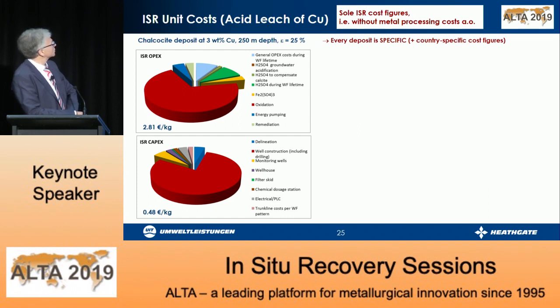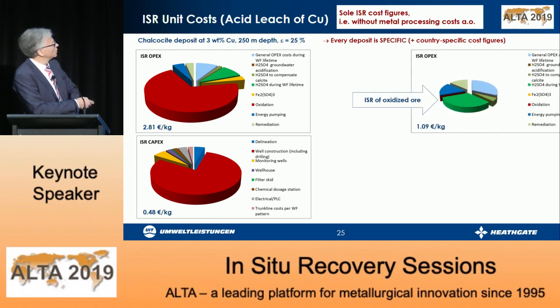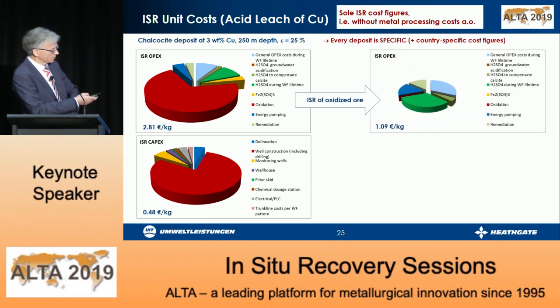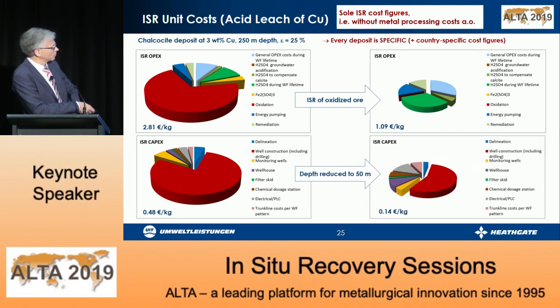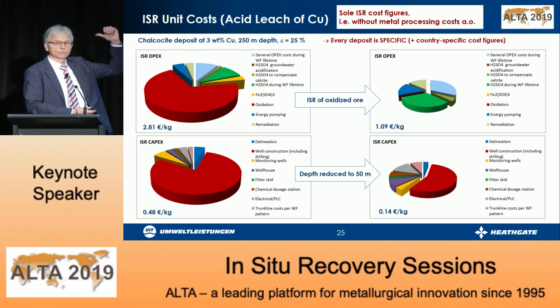So with regard to economic figures, I show here just an example. These are simulated OPEX and CAPEX for a chalcocite and copper deposit under certain conditions, and you see that the OPEX are dominated by the oxidant consumption, the CAPEX are dominated by the well construction costs. And just to visualize what happens if we go to oxidized ore conditions, in the case of copper recovery, then you reduce the OPEX significantly. And on the other side, the depth reduced to 50 meters results in much less CAPEX. You can extrapolate this in the other way.